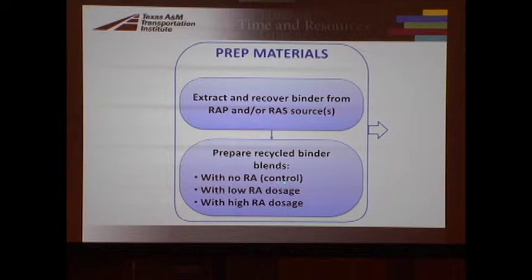With no recycling agent, that would be 0% dosage or the control. With a low recycling agent dosage, maybe around 2%. That's kind of in terms of how the manufacturers of the recycling agents recommend what you do. 2% or less, you basically just add it in there. 2 to maybe 5%, you basically take out some virgin binder and replace it with recycling agent. And so there's this addition versus replacement in terms of how you add the recycling agent.